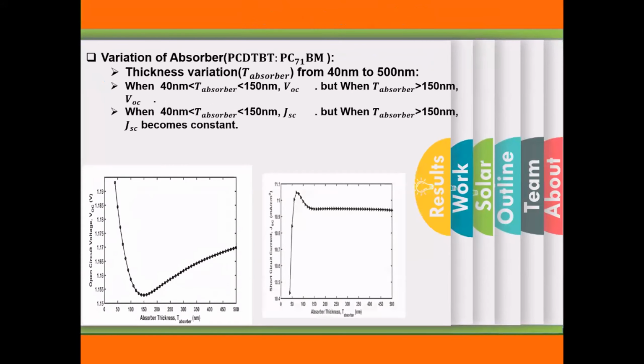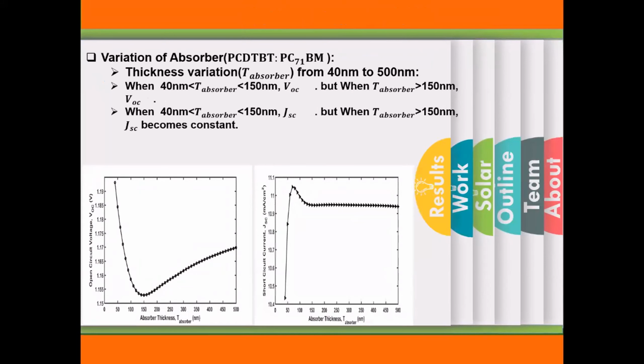Now moving to the results. We varied the two important layers, one is the absorber and the other is the HTL layer. First, we tried to vary the thickness of the absorber, which is PCDTBT:PCBM, to see the possible outcomes and the efficiency, but at that time we kept the HTL layer at a certain thickness of 30 nanometer, while varying the absorber thickness from 40 to 500 nanometer. So we get those outputs.